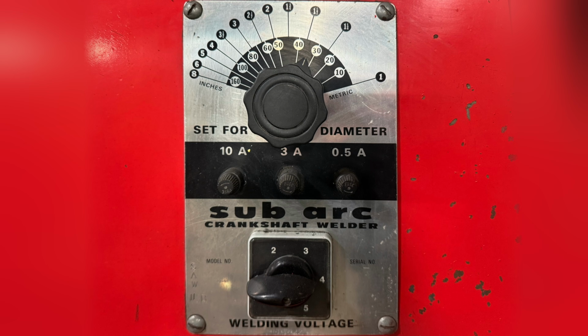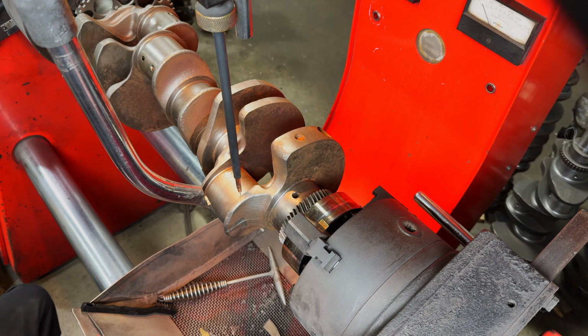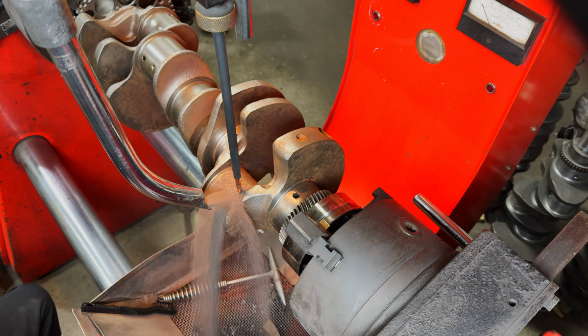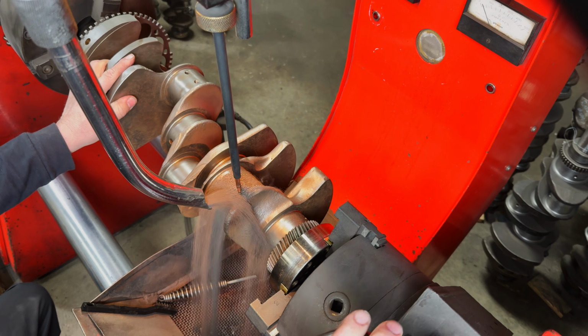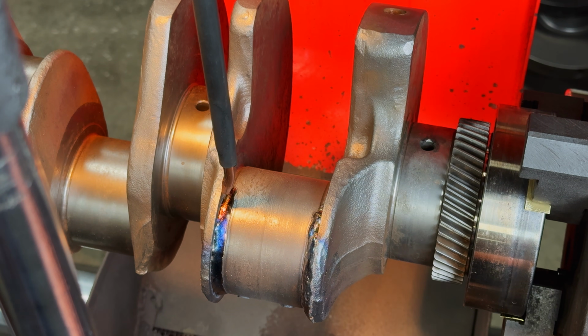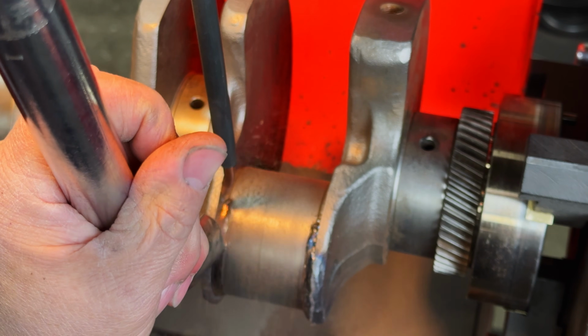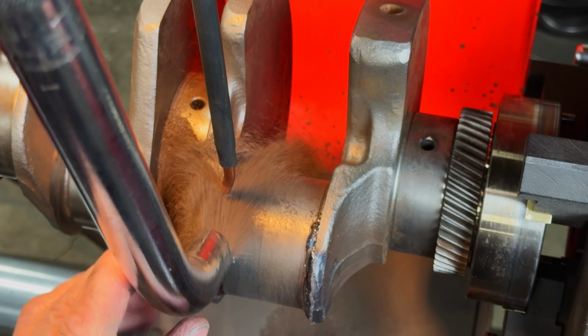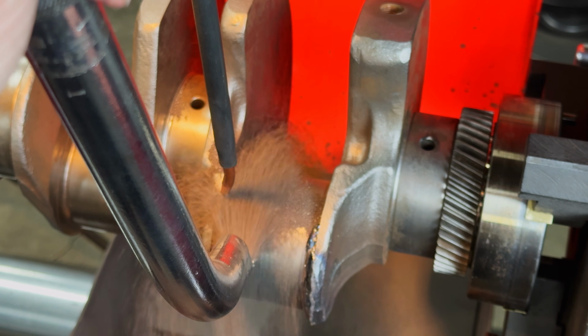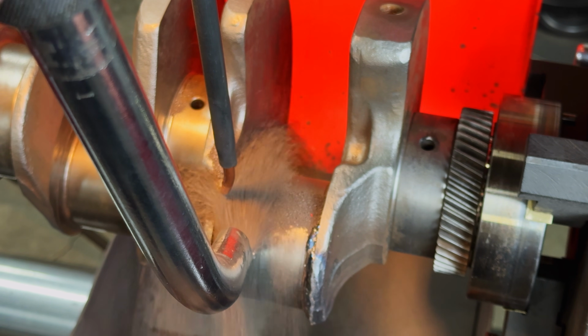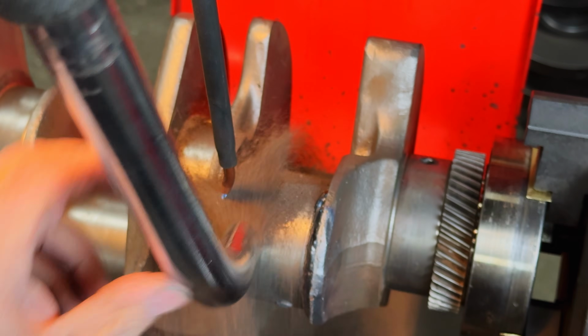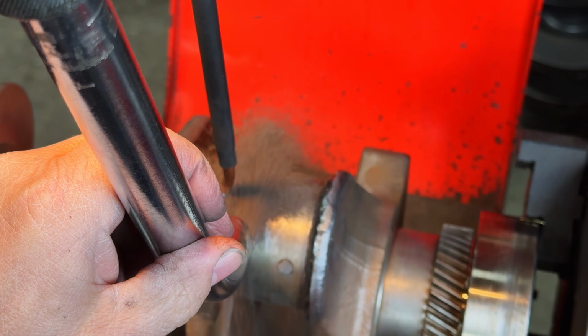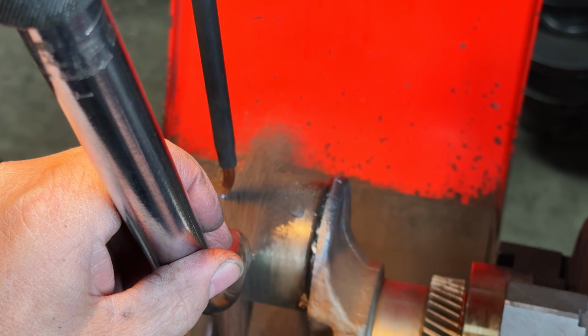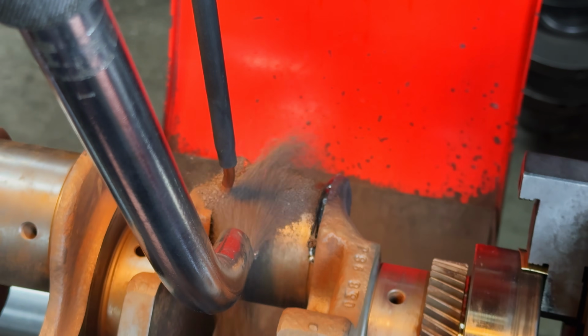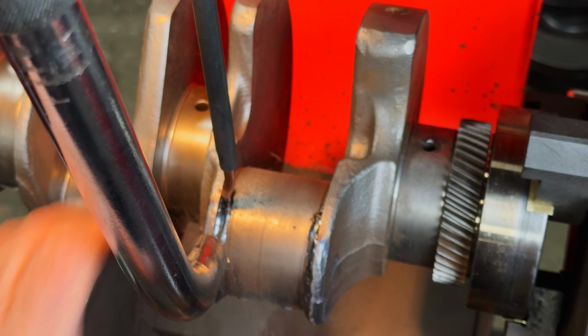Our crankshaft welder is a submerged arc welder. It uses a continuous wire electrode that forms an arc beneath a blanket of granular flux. That flux shields the weld, controls oxidation, and helps produce a high quality result. This is a slow and controlled process. After each pass, the slag has to be removed before continuing. We control the rotation speed of the crank and control the wire feed speed, which determines how much material we're putting down. And we set the voltage on the welder, which controls the arc and helps determine how deep the weld penetrates into the journal.